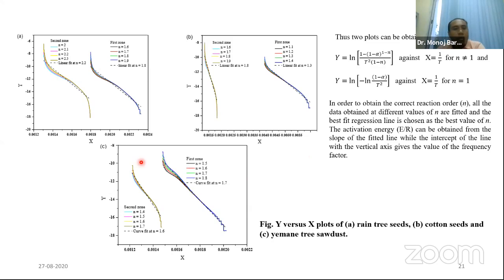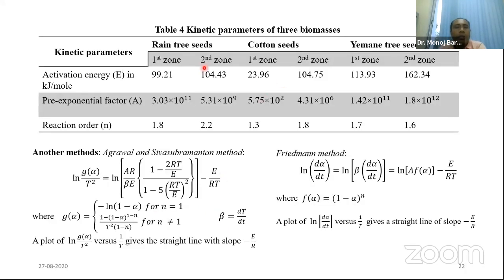So this is how for the 3 samples we estimated the kinetic parameters for 2 zones. For example, for rain-tree seed, in the first zone we got an activation energy of something like 99.21 kilojoules per mole, and for the second zone it is 104, and similarly for the other biomasses as well. We also obtained the pre-exponential factor A for both zones in all the samples, and all these are found for different reaction orders, because in all the cases the best fit line was found for a different reaction order value. For example, in the first zone of rain-tree seed, we got the best fit line for reaction order 1.8. For the second zone, it was 2.2, and so on and so forth.